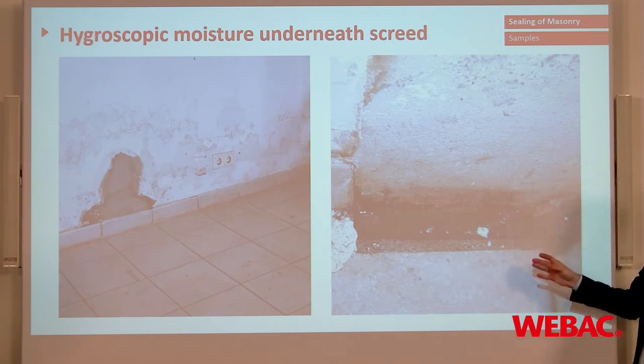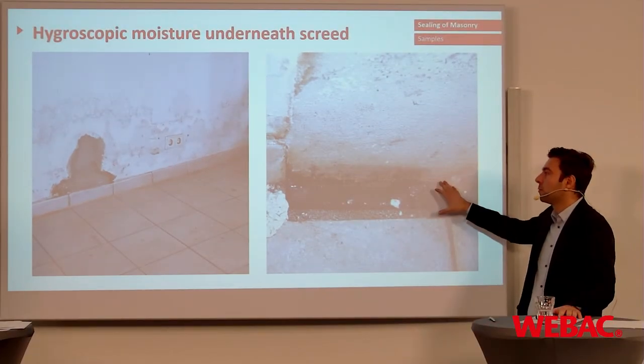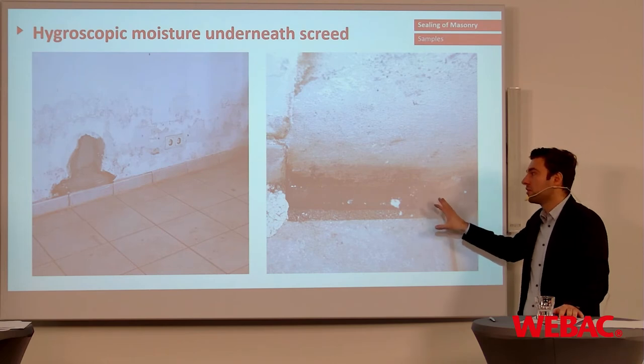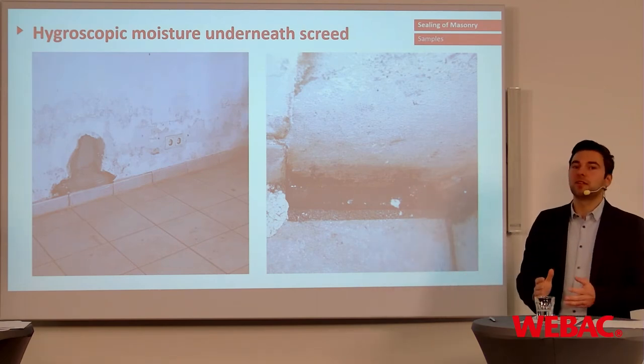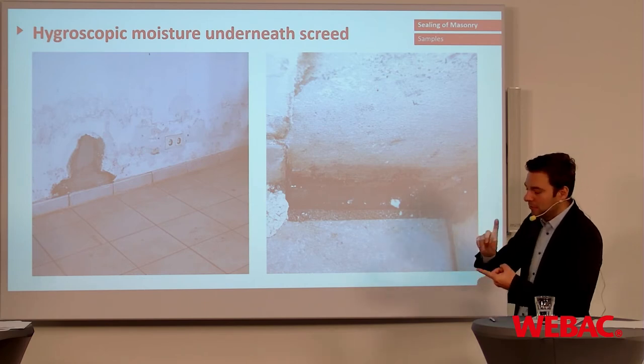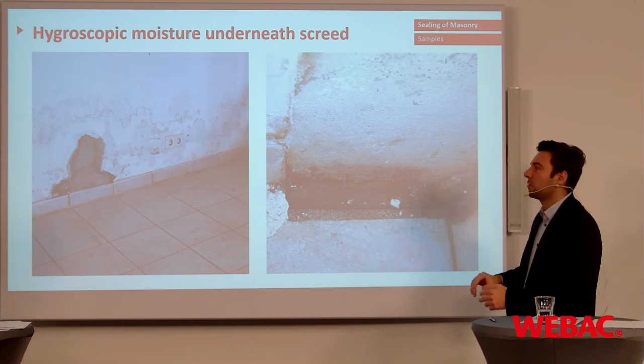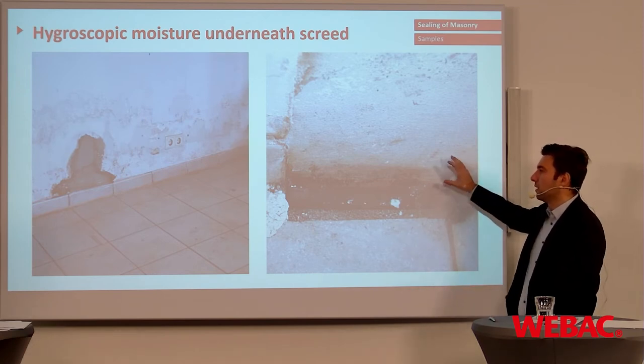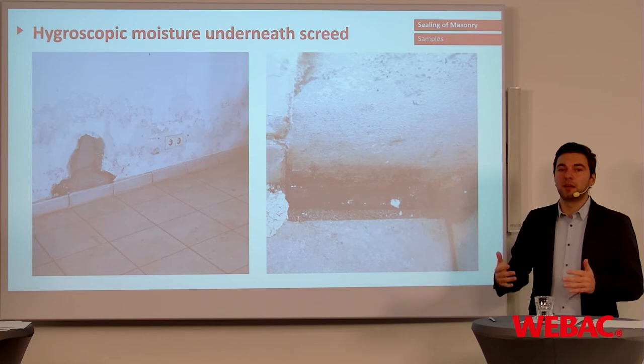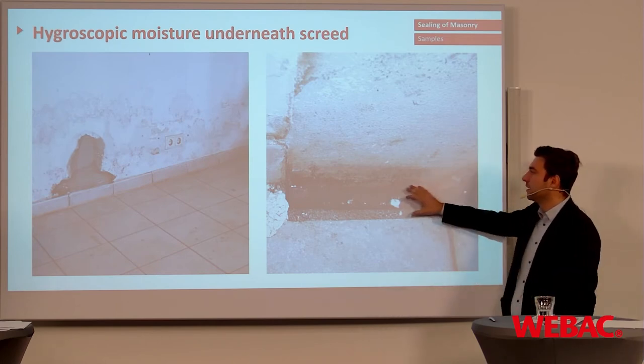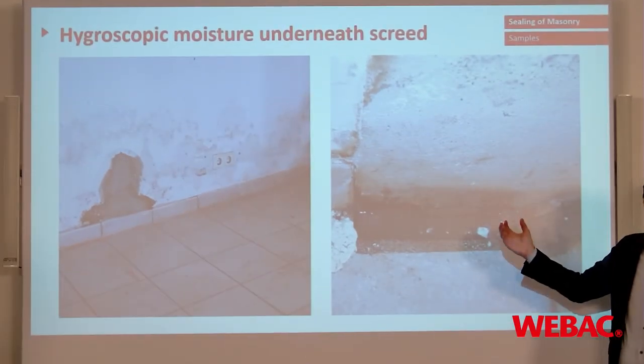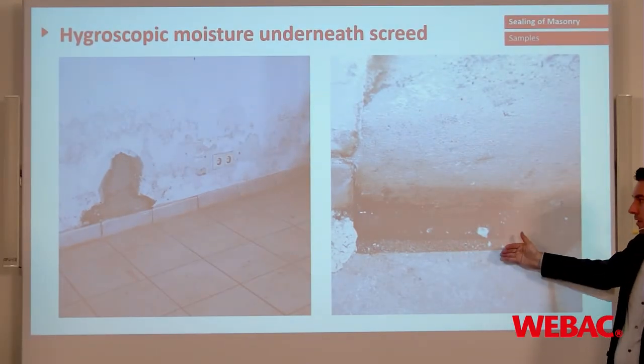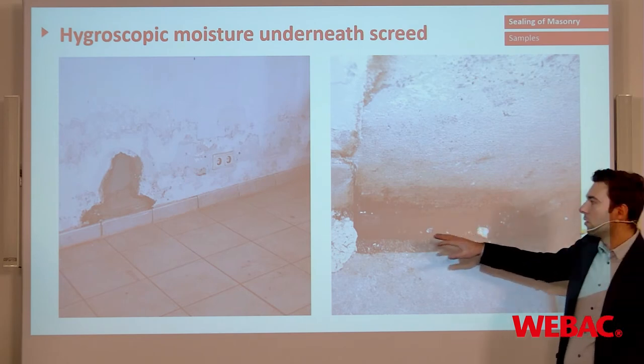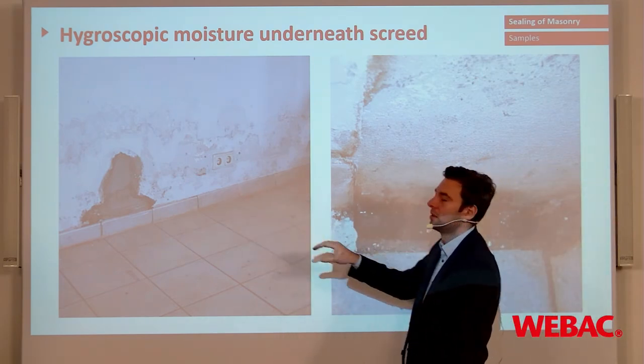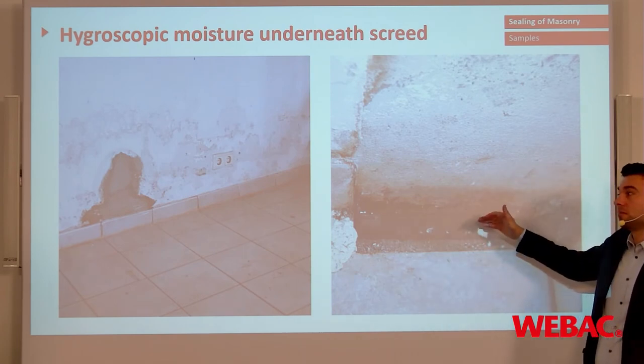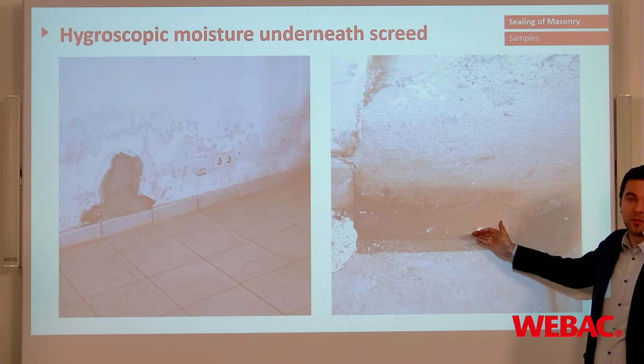And in that case, it was simply that you have the problem underneath your screed. So therefore, it's very important to remove anything that is in front of your building, even if it's tiles or screed. It's always very important to take a look at your masonry itself, not on the parts that are in front or above of it. And you can see it here that there was really hygroscopic moisture on a bigger scale underneath your screed. So therefore, the main problem was not above in the tiles, it has been underneath. So it's once again very important to take a closer look at your building itself.